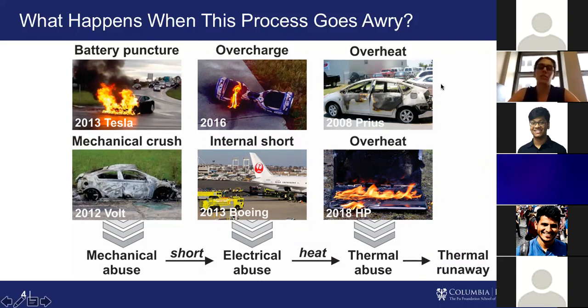So this can happen because the battery is physically at a higher temperature, or because you're charging at an improper rate. And that will also heat up the battery, similar to the overcharge scenario that I talked about before. Again, this causes the system to go into a situation of thermal runaway where the entire device can just spontaneously light on fire.